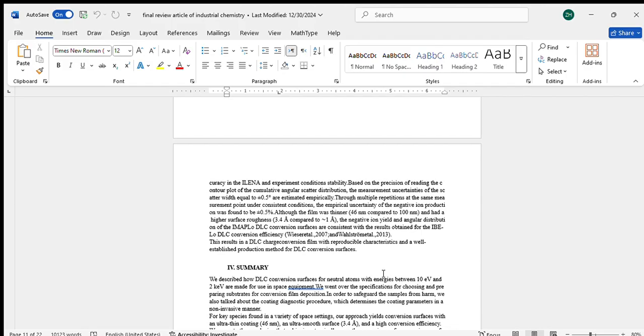Sputter yield, the amount of negative ions produced through sputtering, was measured for helium and neon ions. The sputter contributions were relatively low, ranging from 1.5% to 5% for different ion species. Conversion efficiency consistency: despite differences in film thickness and surface roughness, the negative ion yield and angular scatter for the IMAP-Lo DLC conversion surfaces were consistent.